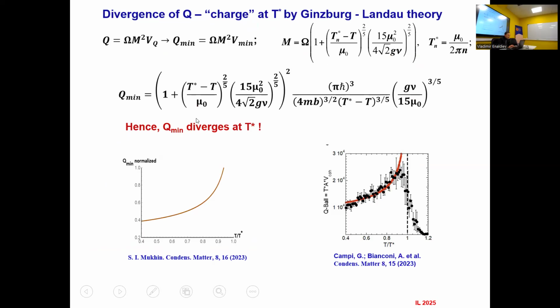Okay, this is what I already told. So this is the behavior of Q mean, and this is how this expression close to T star follows the experimental points, because indeed, when Q minimum goes to infinity, you will see that these experimental points really diverge. And what is here is, of course, questionable, but this is above T star. So this is the theoretical curve, and this is the same theoretical curve with the experimental points. So it means that these experimental points actually show that indeed the superconducting condensate of Cooper pairs appears inside the Q-ball, and when we come close to the temperature when it appears, the Q minimal value of the Q-ball diverges, and that's why these points diverge.